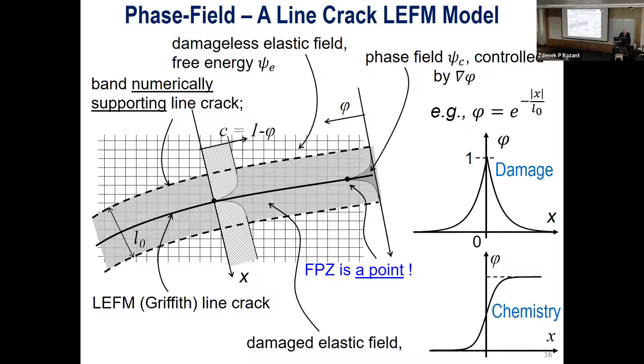So phase field is a model which first occurred in chemistry about 50 years ago to approximate surface chemical reactions, which actually essentially represents a Heaviside step function, and it was distributed smoothly, and then variational methods could be used to model it very effectively. Now in fracture, we have a line, so the line crack is a Dirac delta function, and it is smoothed out by damage, like this, a damage parameter. And that damage parameter has the purpose of anchoring the line to the finite element code to run in any direction, without any bias. We know normally there is a bias.